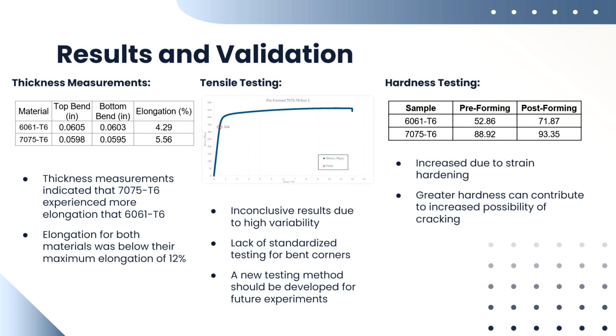7075 T6 showed more elongation than 6061 T6, meaning it thinned more during forming. However, both stayed below the 12% max elongation limit, so no overstretching occurred. Tensile testing results were inconclusive due to high variability. Since there's no standard method for testing bent corners, the data wasn't fully reliable. Future work should develop a more consistent testing approach for these regions.